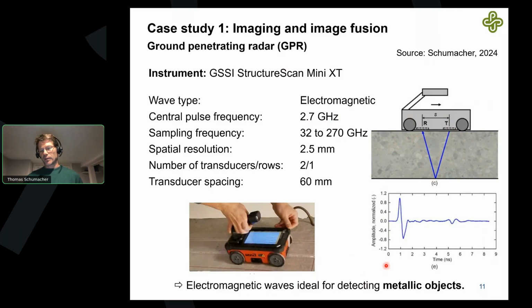Electromagnetic waves are really optimal at detecting metallic objects. So we're looking for dielectric differences between materials. You do get a decent reflection from an air surface as well, but it strongly reflects from steel. That can be a problem sometimes. If you have a very dense steel rebar mesh close to the surface, that can reflect all the energy back, and you can't really see very deep. But it's ideal to detect rebars or other metals.